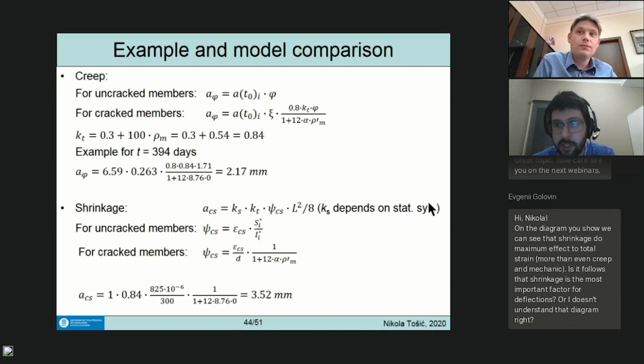But the effect of shrinkage on curvature doesn't follow just from the strain value, it also follows from the distribution of reinforcement. So even by adding a little compressive reinforcement, you would reduce this curvature because you'd change the moment of area of reinforcement, since here we only have tension reinforcement. In this case, yes, the effect of shrinkage is very high.